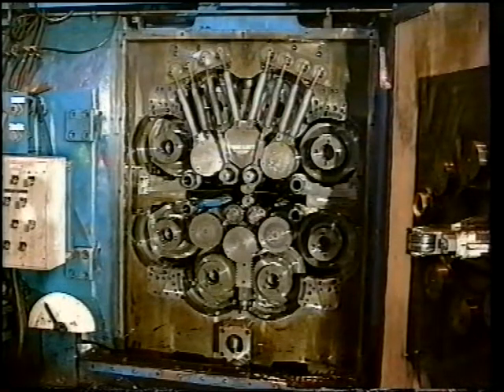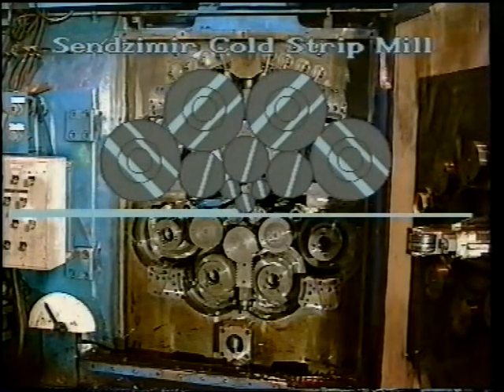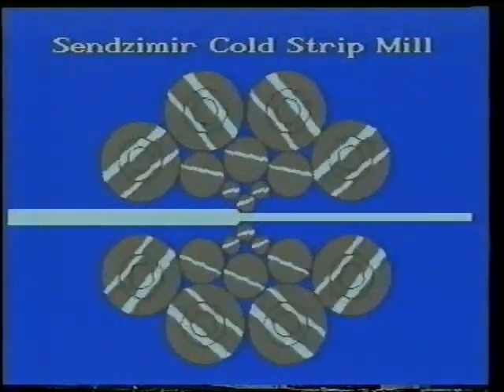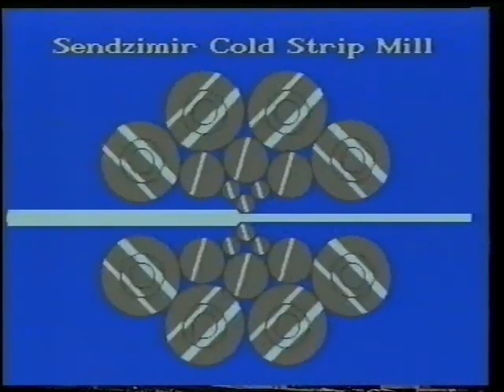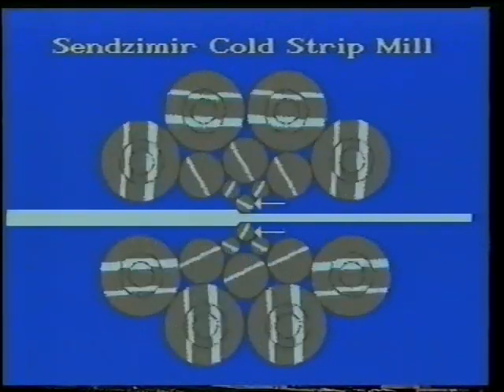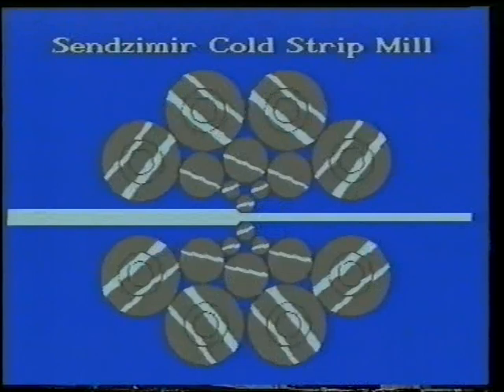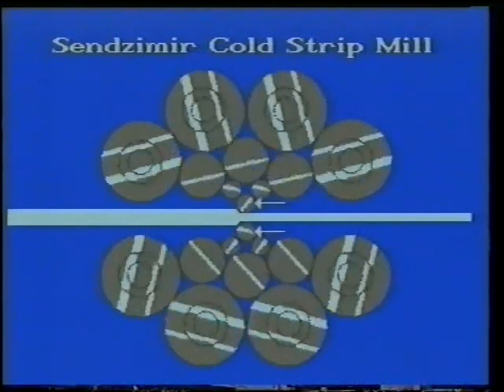The housing, which weighs approximately 110 tons, is fitted with upper and lower 10-roll cluster arrangements, the normal work roll diameter being 85 millimeters. The use of such small diameter work rollers gives a high arc of contact, which enables greater reductions to be made on each pass.